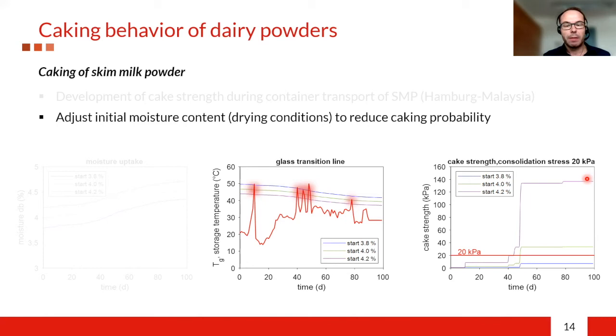So from this, when you expect such a temperature or humidity profile during transportation, it's necessary to adjust the initial moisture content, for example, by changing the process conditions to reduce the caking probability. So in this case, you should reduce it to below 4% when you have such a temperature profile in the container.